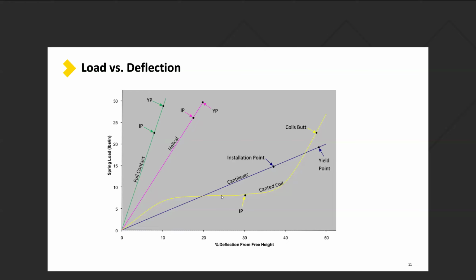The other interesting thing about the canted coil spring, you'll see from this chart, is the other springs reach a yield point, whereas on the canted coil, the coils butt together. So instead of the spring yielding, you'll go metal to metal, your force will shoot up, and really that coil butt happens around here somewhere. But that force will shoot up significantly. But if you take that compression away, the coils can open back up, and the spring may not have yielded at that point, and the seal can still be salvaged. Whereas these other ones, once you reach that yield point, the seal is done. The spring is damaged beyond usability. We'll talk a little bit more about these characteristics a little bit later.